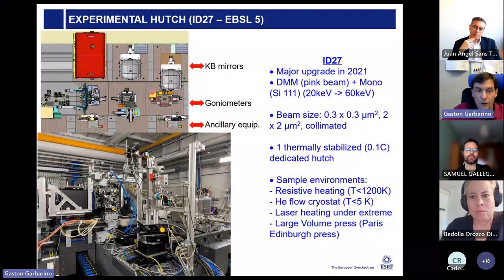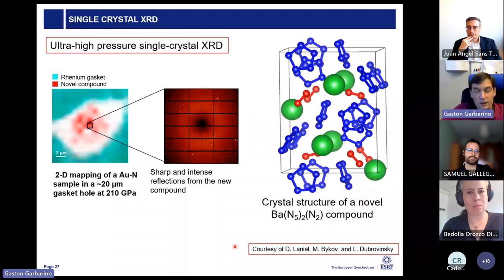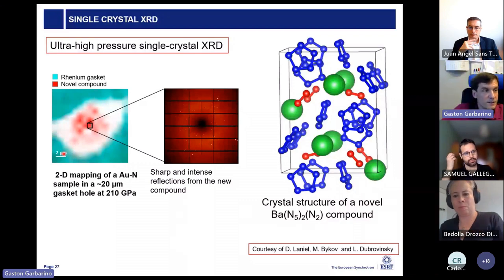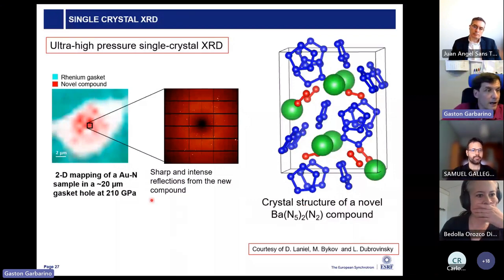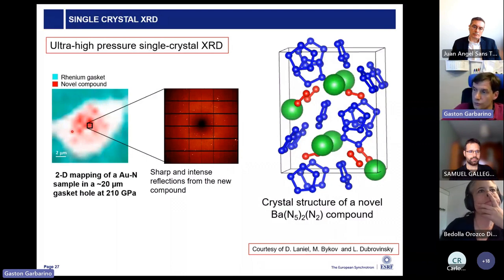So I would go to some examples now, and the first is that, as the beam is quite small and very focused, we are able to really map samples that are very inhomogeneous. For example, here you can see a sample at 200 GPa, 2 million atmospheres. It's a reaction between gold and nitrogen. Each point of the sample is a little bit different. It's not fully homogeneous due to the synthesis, and we are able to do single crystal diffraction on these very small peaks. One example is the solution of the structure of this barium nitrogen compound.